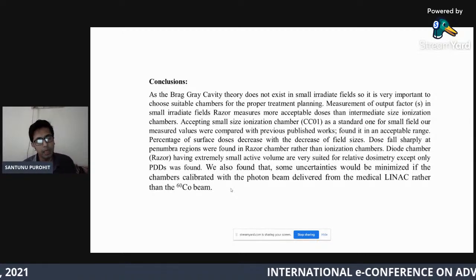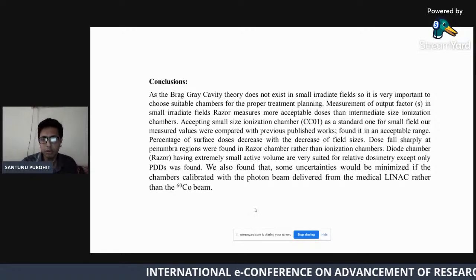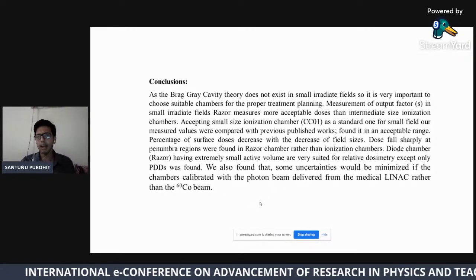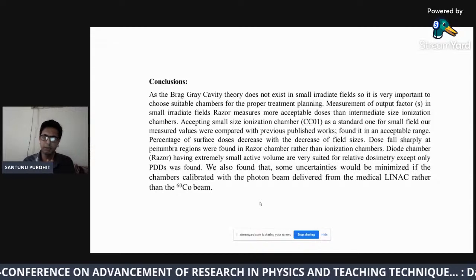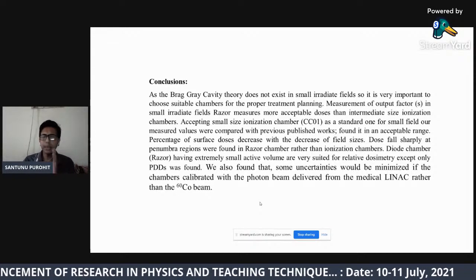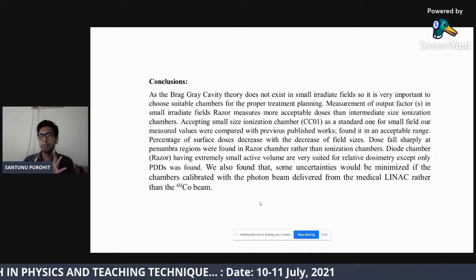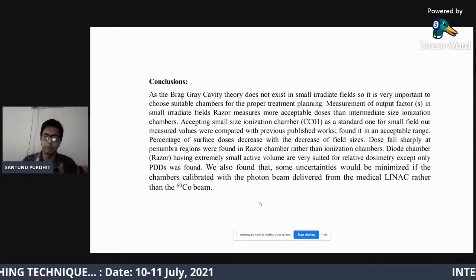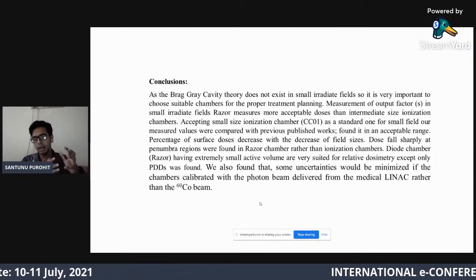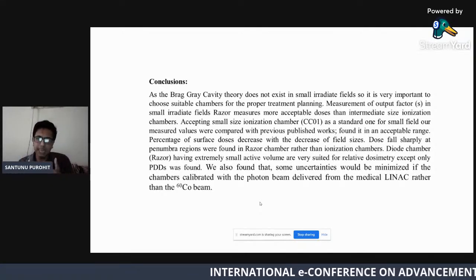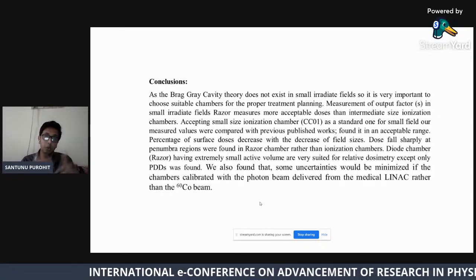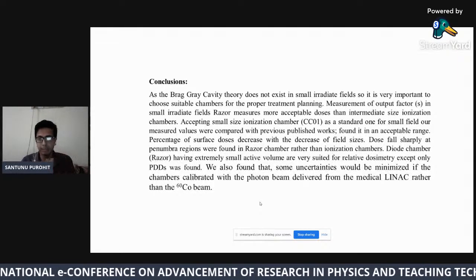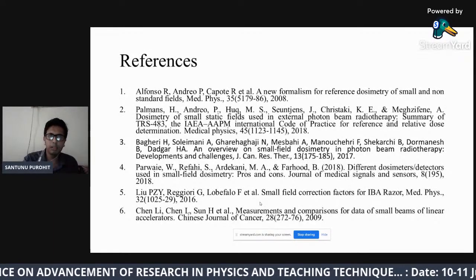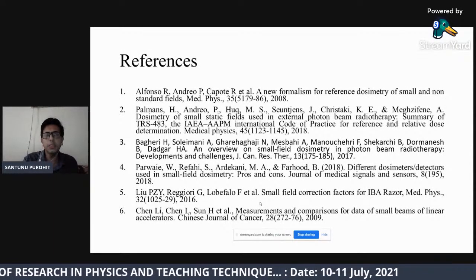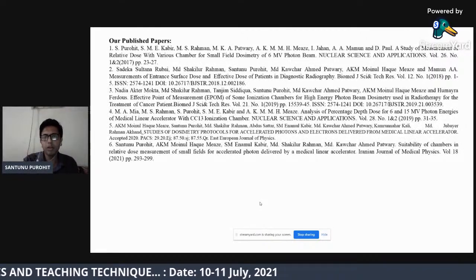You see in my PDD curve. So we found that some uncertainties we can minimize in this technique. How? If we calibrate our chamber with a medical linear accelerator rather than a cobalt beam. If we change this cobalt beam into the medical linear accelerator and calibrate our chambers through it, then some uncertainties will be minimized. And these are all the references used throughout my presentation, and these are all my published papers on small field dosimetry. And thank you.